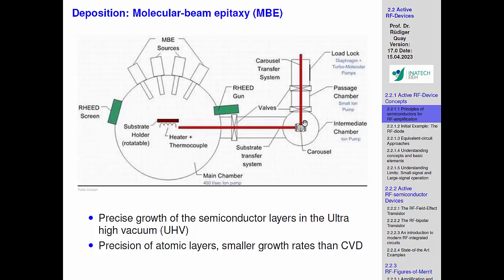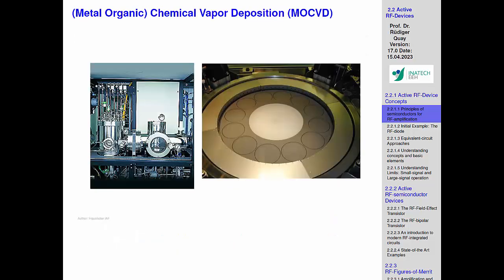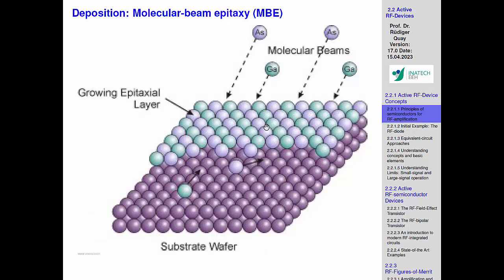And you can actually see this. This is the monitoring of the growth, because there's a RHEED system. The idea is that you diffract electrons on the surface, and during the MBE growth you are constantly changing the surface. When a step of a new layer is formed, the electrons diffract, and you get an image, so you can actually observe the growth atom by atom on a pattern of diffracted electrons.